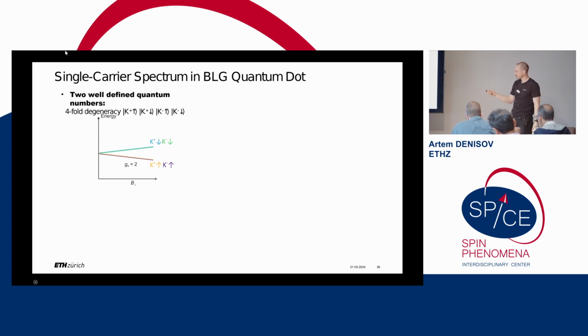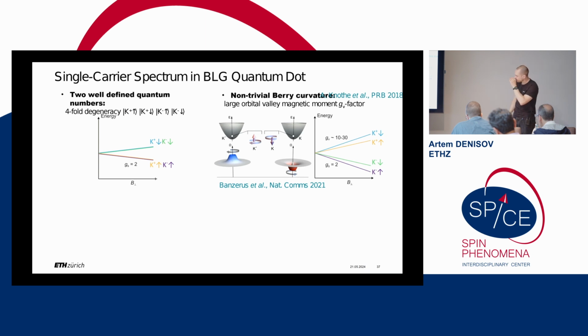Thankfully, it's not the case, because in bilayer graphene we have a non-trivial Berry phase, which you can acquire if you go across one of the K points. In practice, you can summarize it as there being a valley G factor, meaning that as you increase magnetic field, your K plus valleys go up, your K minus valleys go down, with a very high G factor of 10 to 30, which can also be tuned electrostatically. So now the spectrum looks like this, already a bit more interesting.